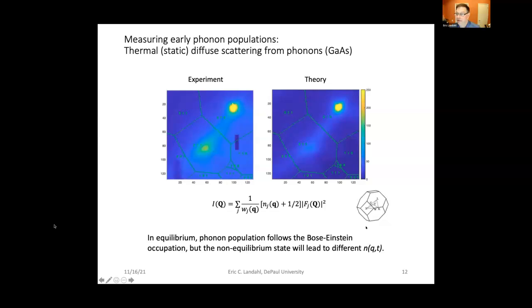The first check is to look at static thermal diffuse scattering, where the phonons are simply populated by Bose-Einstein occupation numbers. Our experiment shows here at the center of 2 adjacent Brillouin zones under static conditions the sorts of patterns that you would expect from theory from thermal occupation numbers at room temperature. Different distributions of phonons then will lead to different locations in terms of both angle and time as those distributions evolve, and therefore different locations lighting up in the diffraction or the diffuse scattering pattern.